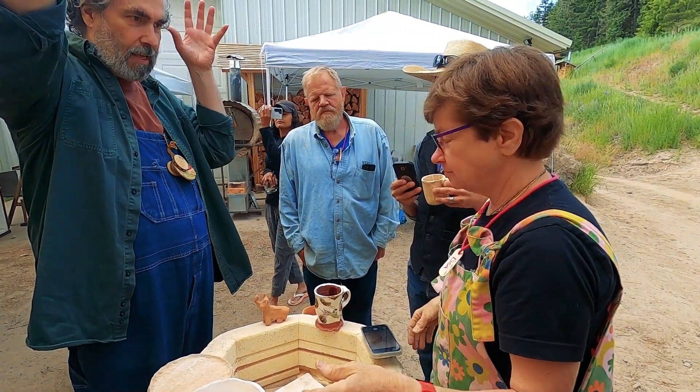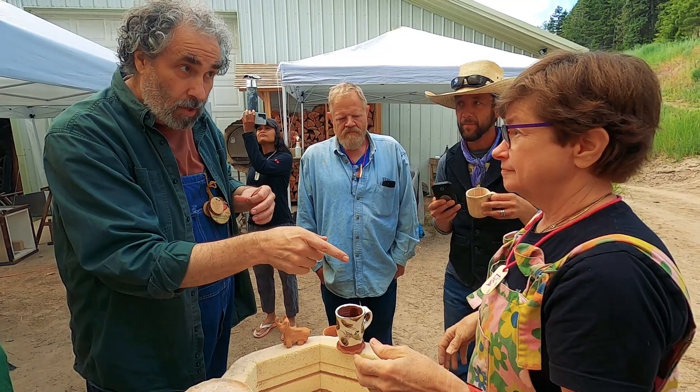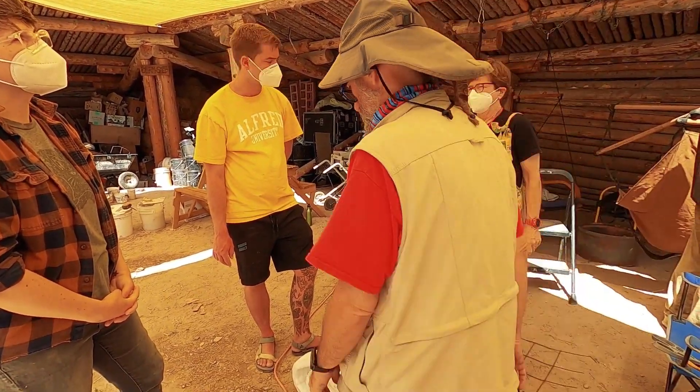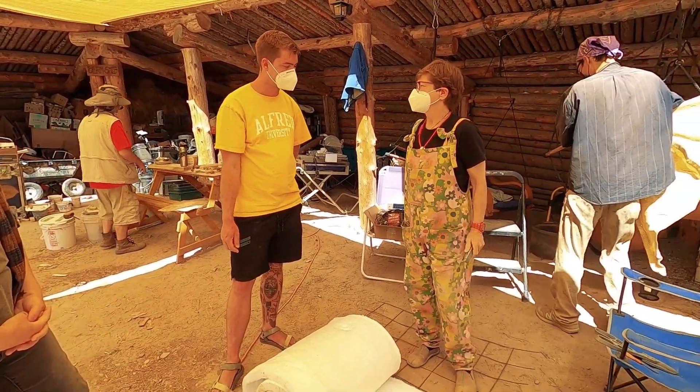This is an option that could be fired year-round in town — there's no need to be stealthy, but it's safe. The fire is very contained; there's nothing on the outside. I use an industrial porcelain that I make from scratch that does best with less warpage and less cracking if I fire it as fast as the kiln will go. Normally I'm somewhere between four and a half and five hours up to top temp, and we hit that in under five with this kiln yesterday. During our unload today the work looked very similar if not the same as it did out of an electric kiln — that costs thirty dollars of electricity every time I fire, plus you have to buy a kiln and hook it up. There's a three to five thousand dollar upfront expense to purchase an electric kiln, and this was an old piece of junk that's really got value now. Very basic technology that works shockingly well for ceramics.